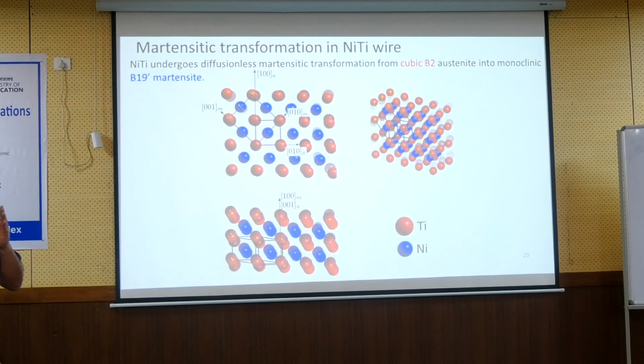As I said in the literature, this article in Nature by Chluba et al. about the cofactor is kind of influential, and many people believe that this is the case. What they predict is that if you add copper to NiTinol, you will change the lattice parameters and you will make the strain compatible at the interface. But in fact, the situation is a little bit different, and we now believe that even in NiTinol,